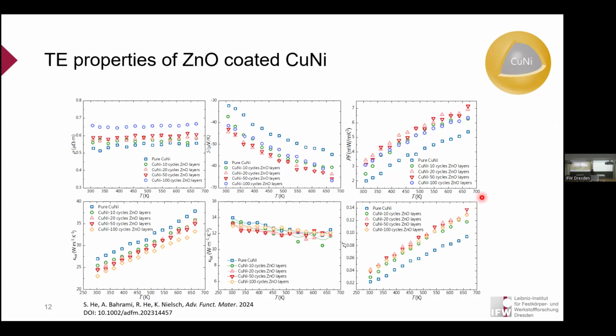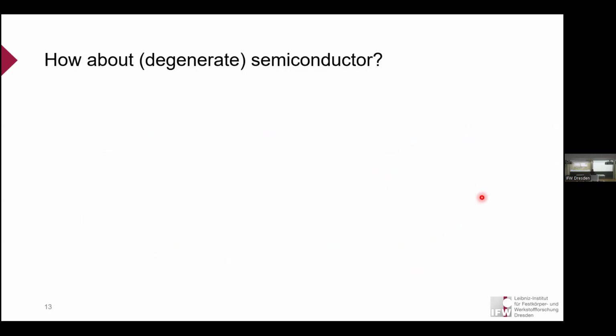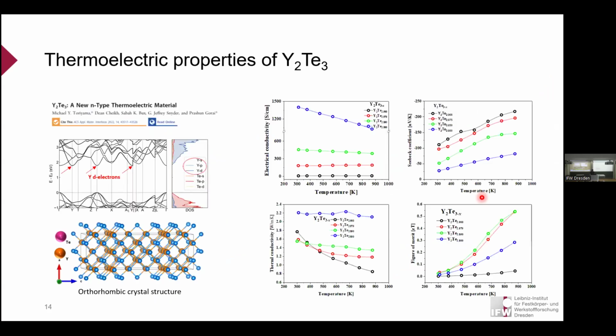And particularly, we're interested in degenerate semiconductors, right? And this is a very recent work. We just submitted it, and it is still in the process of review. Basically, it's dealing with rare earth chalcogenides, yttrium telluride. This material was initially predicted through a machine learning assisted calculation, followed by much more detailed calculation for the band structures. And you could see that the N-type material has a valley degeneracy at the conduction band minimum. So that means it's predicted to have very good N-type properties.